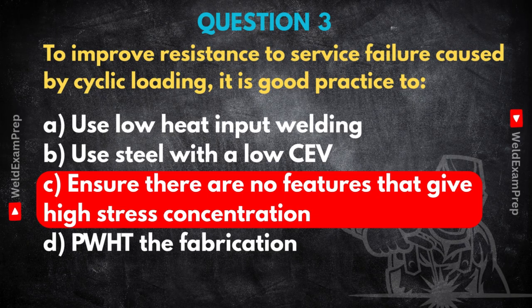Primarily, yes, but fatigue cracks almost always initiate at a geometric stress concentration. A sharp corner is still a sharp corner, even if the residual stress nearby is low. The applied stress under cyclic load will still get magnified hugely at that point. So PWHT doesn't remove the starting point for the crack. Correct. It doesn't eliminate the initiation site. So while PWHT helps, and things like low heat input or low CEV steel improve toughness or reduce cracking risk, important things, for preventing the start of a fatigue crack under cyclic load, rigorously minimizing those geometric stress concentrations is the number one priority. It's about preventing the first shot, so to speak. Got it. Build in the resilience from the start in the design and execution.